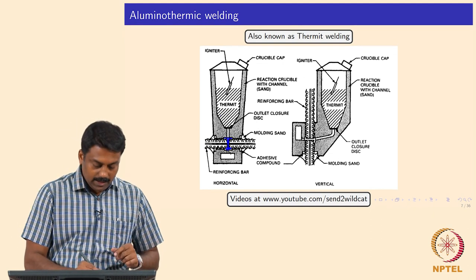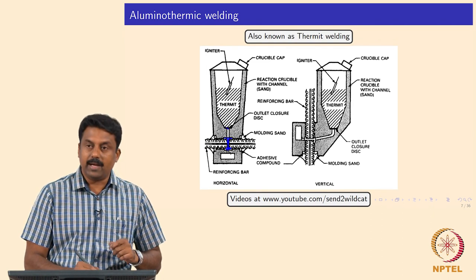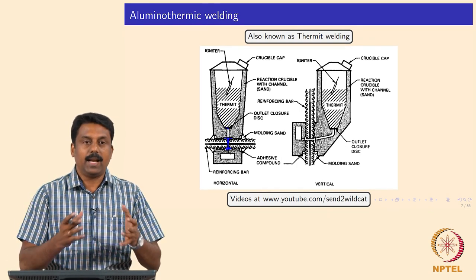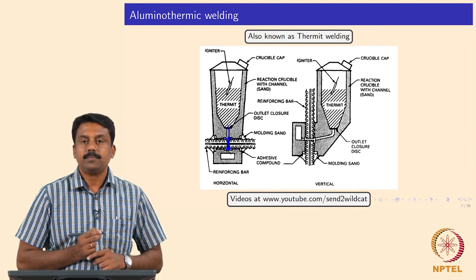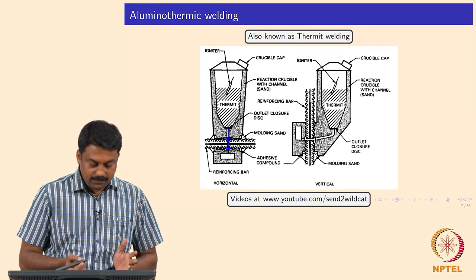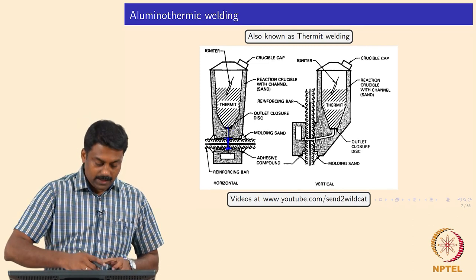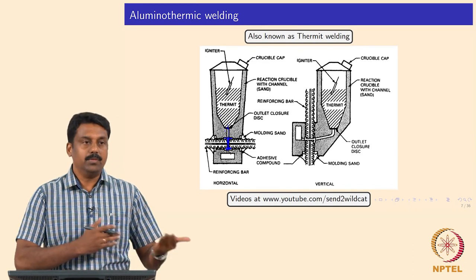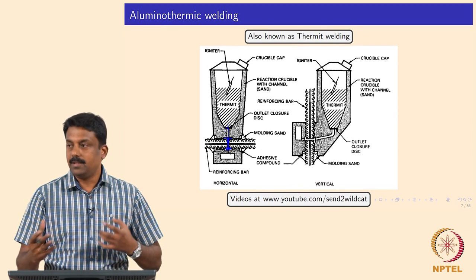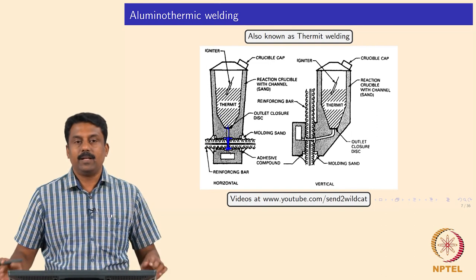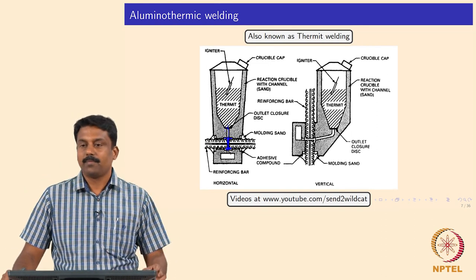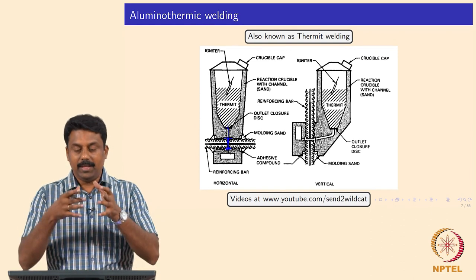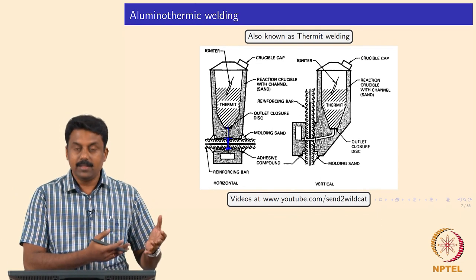Subsequently, there is an opening which works on the principle that once the temperature goes above a certain threshold it cracks open, and liquid metal starts filling the weld cavity. Once the weld cavity is filled, the crucible mold can be broken out and excess material shaved off. Then simple grinding ensures there are no sharp edges, and ultimately the weld is as good as any cast structure.